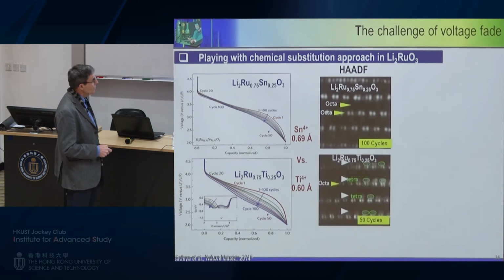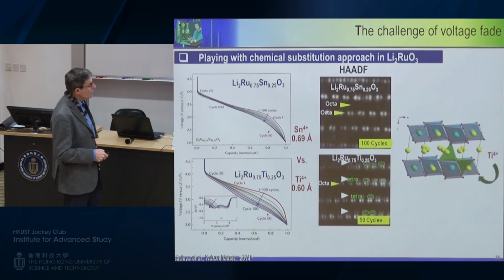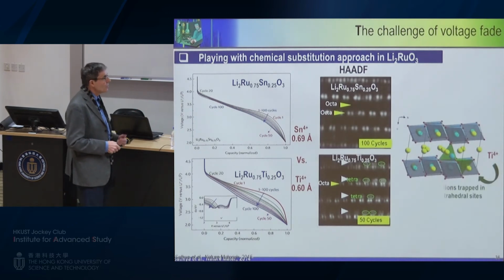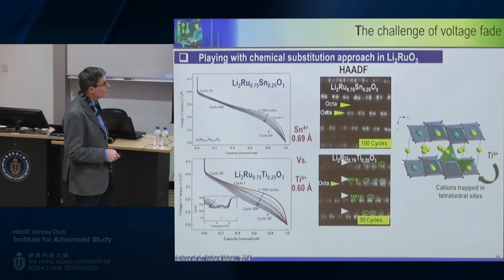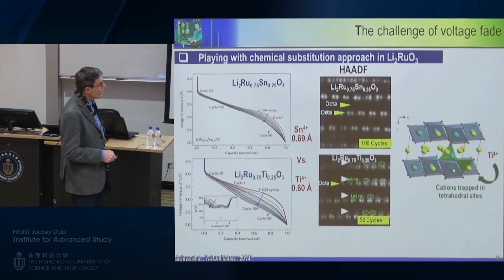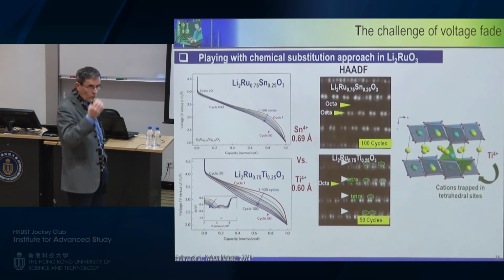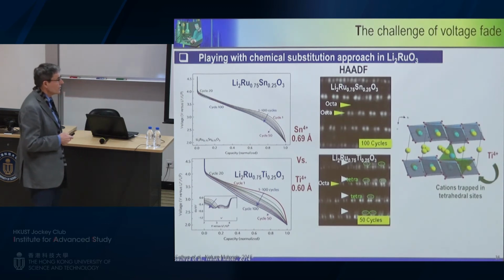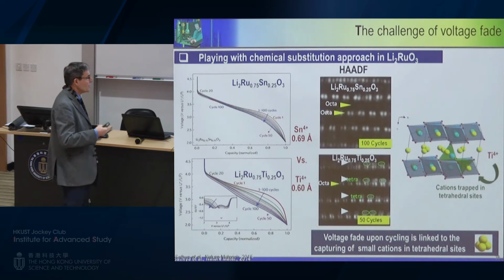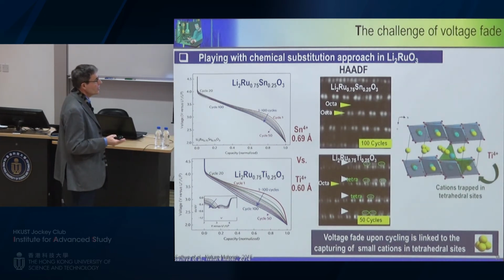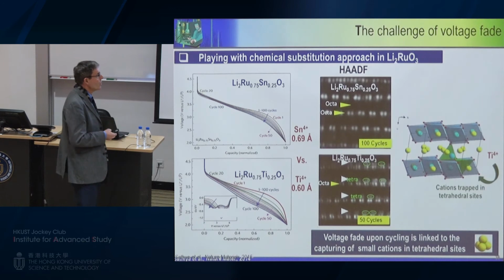If you take the same compound with titanium, as clearly indicated here, look what is happening here. You have nearly the same row, and here you see this kind of white spot, which corresponds nearly to the tetrahedral site in the structure. So what is happening here, when you have titanium, look here, when nearly you are removing lithium from the structure, titanium is migrating from the metal layer to the van der Waals layer, and since titanium is relatively small, it gets trapped into this nearly tetrahedral site. And this explains why we have this kind of voltage fade. Since we understand the origin, we are able, as we'll see later, to propose a solution.